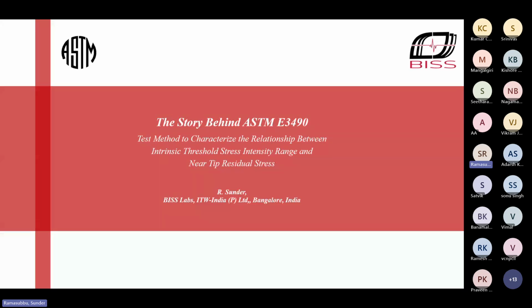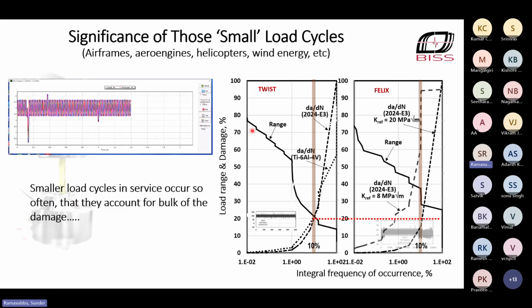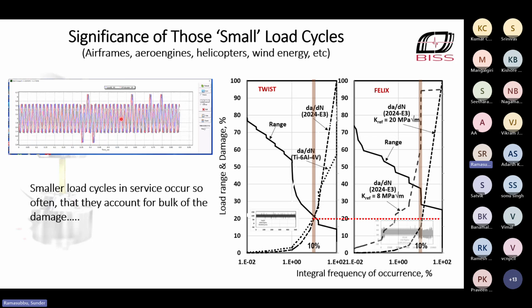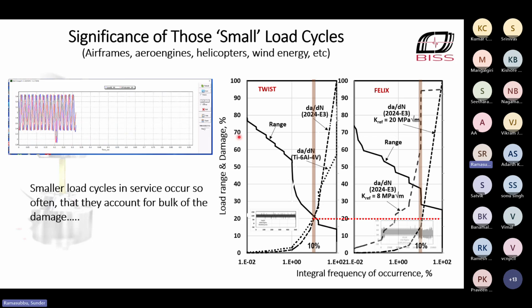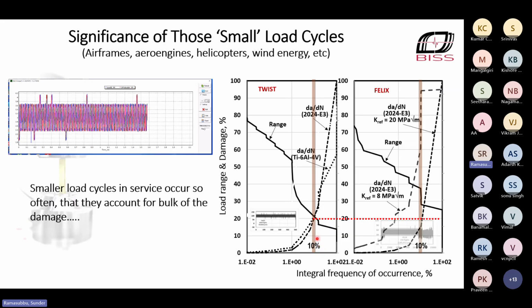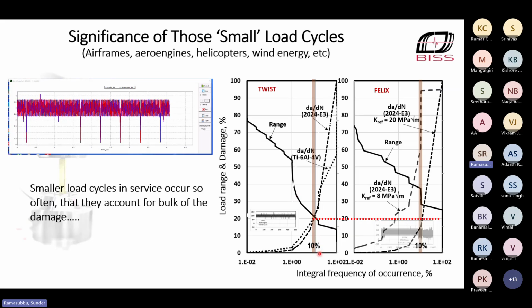Okay, let me not waste any more time. On this first slide, I'm trying to show you on the vertical axis how a load spectrum looks in real life for, say, an aircraft wing. It turns out that most of the damage is actually caused by small cycles. You can see this is the damage curve, and that is the load exceedance curve, and the smallest 10% of the amplitudes of cycles cause 80 to 90% of the damage.